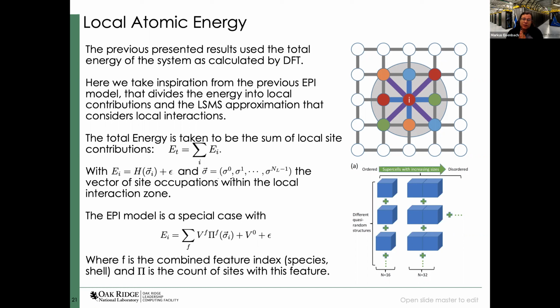Now, it turns out that it is very important for us here to train not only on simulations from one single simulation size, but from DFT calculations on different size cells. That actually helps us to reduce spurious small supercell periodicity errors, and helps in the generalizability of the model.